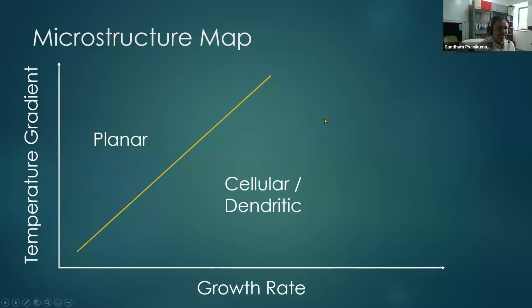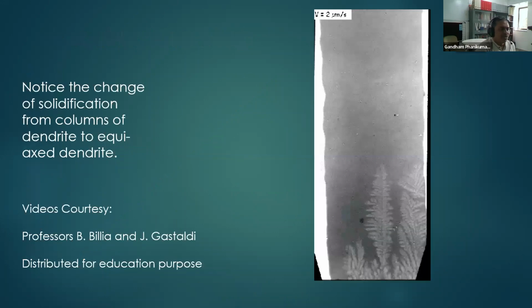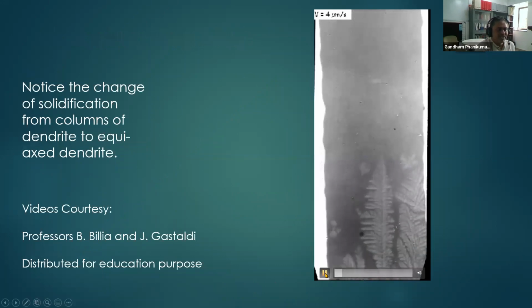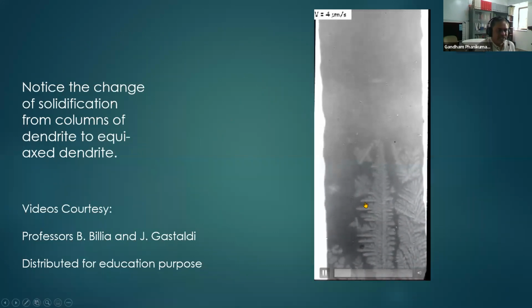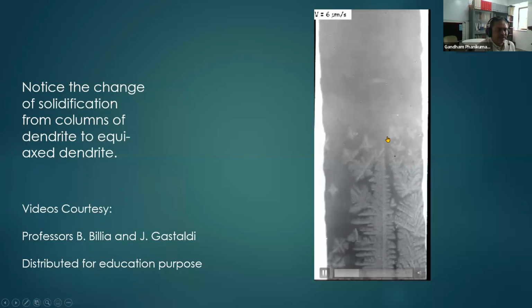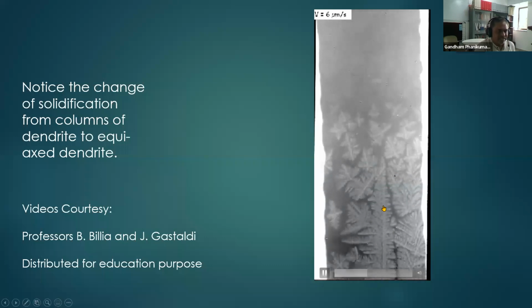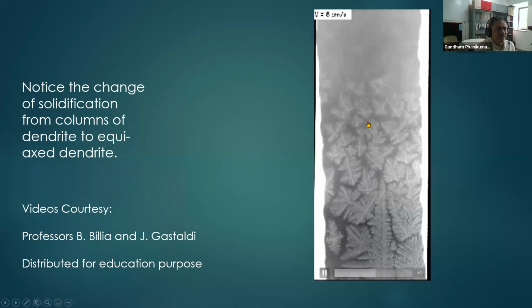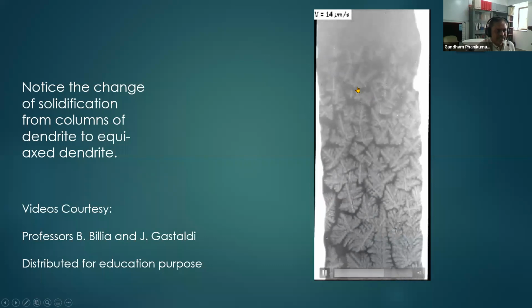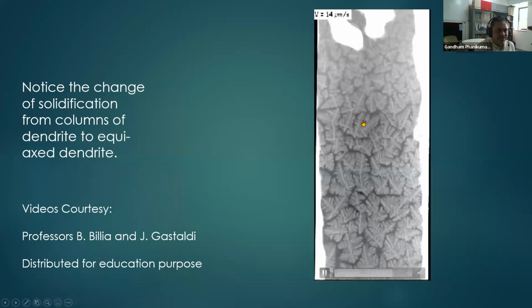And that is a play that we would like to use in additive manufacturing to get either a single crystal or a very equiaxed fine microstructure. Now, the equiaxed microstructure formation is evident here. Whenever the undercooling or driving force is available in front of the liquid, instead of these grains and dendrites growing, you will have new grains nucleating in the front. So equiaxed microstructure can form.